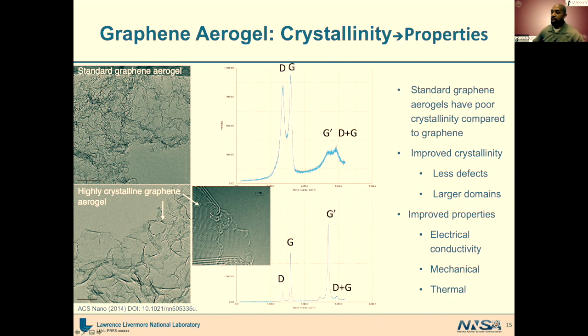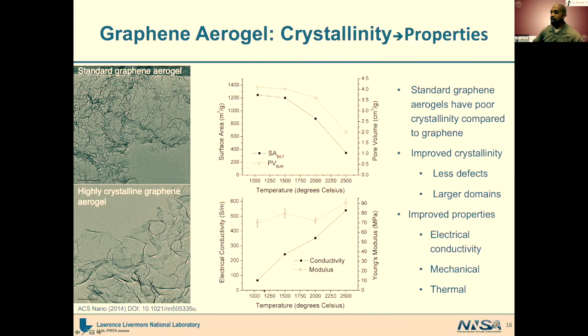And so when you then take this material and heat it in excess of 1500, 2000, or even 2500 degrees C, you actually start to anneal out those defects and get to this very highly crystalline graphene, which you can now look at at the atomistic scale and see how highly crystalline it is. You have much larger domains of single crystal graphene, and that is evidenced here in the Raman spectra, but also in the properties. So in the next slide, you're able to see that the conductivity goes up very significantly. And then you also get a slight, modest increase in the modulus as well. And so this is just showing another way in which you can really tune the properties.